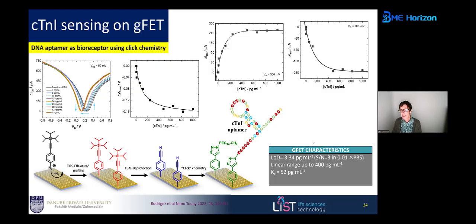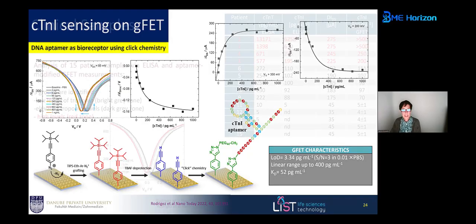What you get here is a limit of detection of around 3 to 4 picograms per milliliter. So we are really in the detection range where we can distinguish between healthy and onset people, with a linear range to around 400 picograms. So we just about make it to tell you if you're really a high-risk person. So this is what we did.